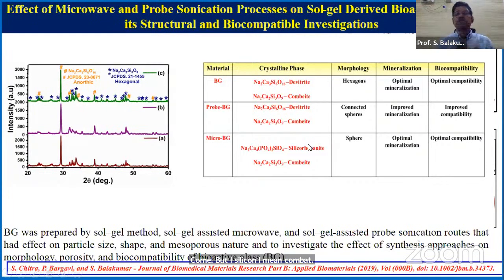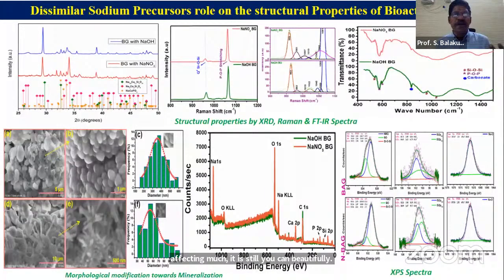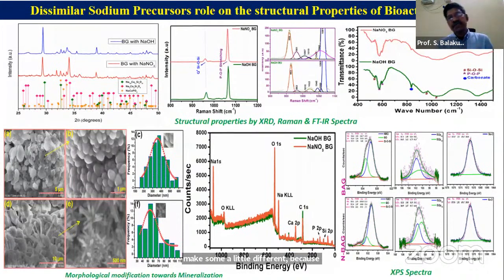But what is the ratio that you require? We found that if the ratio is not affecting much, you can still use it beautifully, and the mineralization you can do within 21 days. And we also know that when you prepare a slightly bigger compound with many different materials, the order of precursor, and the type of the precursor, also makes the material different, because that certainly changes the alkaline nature of the material and pH. That certainly affects the material formation.